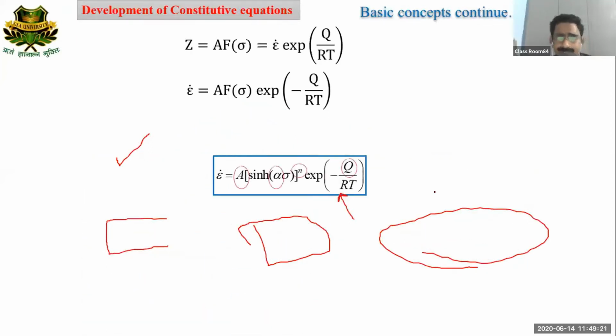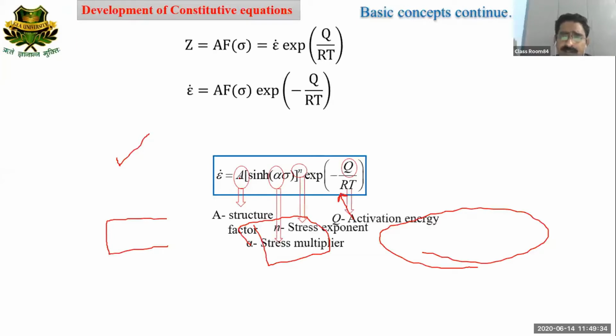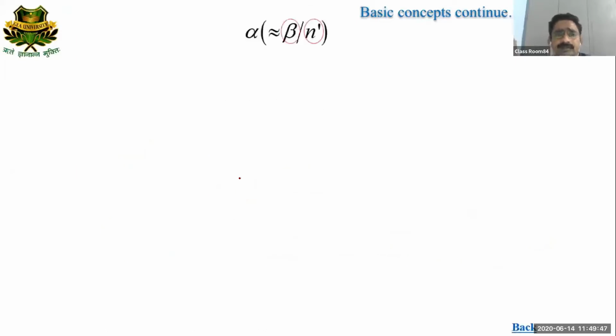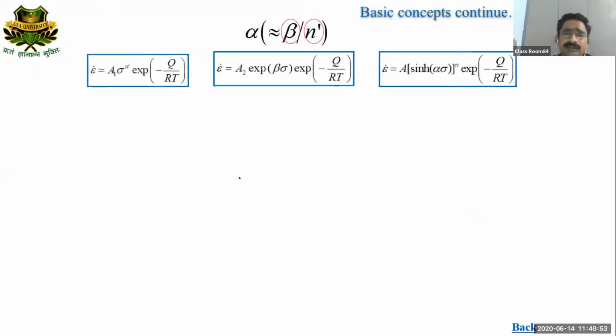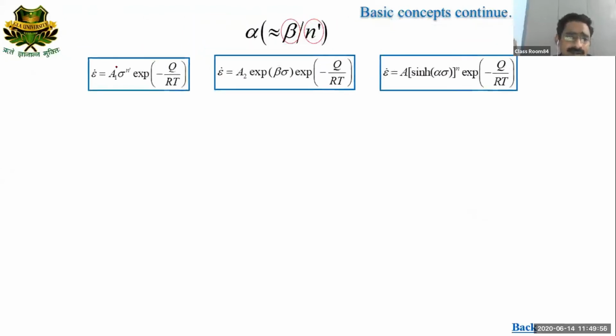So now the question is, how can we calculate all these parameters like the structural factor A, the alpha value, which is known as the stress multiplier, n the stress exponent, and Q the activation energy. These are the four parameters we have to calculate. We have to do a little analysis to get these values. To calculate alpha, we must have the values of beta and n dash. So how can we get the values of beta and n dash? n dash we can calculate from this equation, just by simplifying it. And the beta value we can get from this equation, also by simplification.